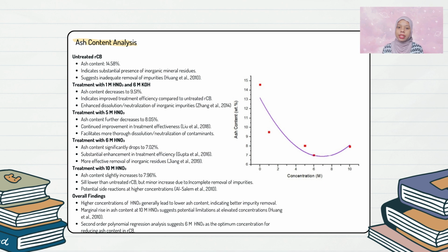Next, we examine the ash content of RCB before and after treatment. Ash content is a critical parameter as it indicates the presence of inorganic impurities which can adversely affect the properties and the performance of RCB. Our results showed a clear trend. Firstly, untreated RCB had a relatively high ash content, reflecting the presence of various inorganic contaminants from the pyrolysis process.